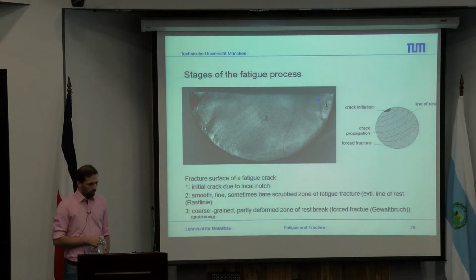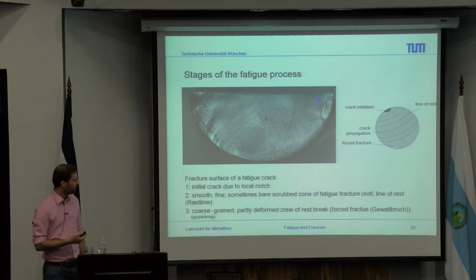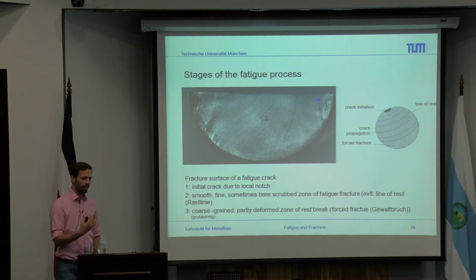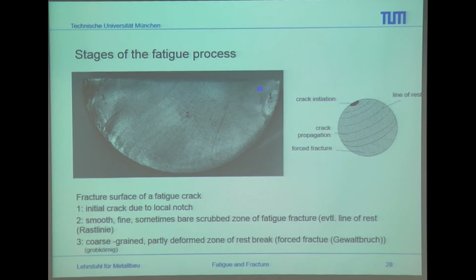So then, what are the stages of the fatigue process again, but from the view of what I can obviously see on the specimen I tested in the laboratory. The testing in the laboratory usually looks like this. This is a round bar, tested in a normal fatigue test with sinusoidal loading. And you can see here at this part the crack initiation. This is a small part. You have some local deformations or some failure in the material. And at this part, due to the failure in the material, you get the first cracks. And at the end, you have some crack propagation.